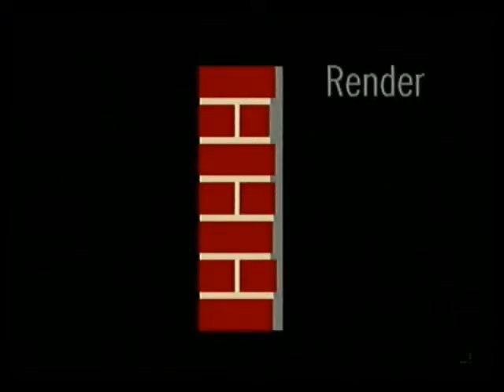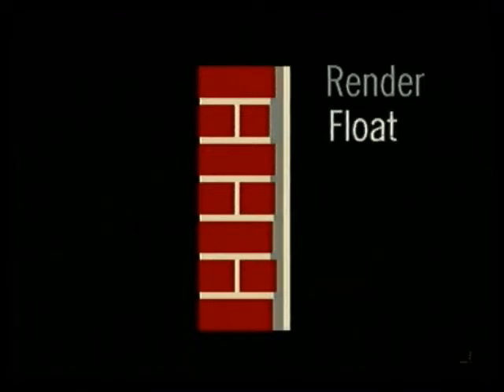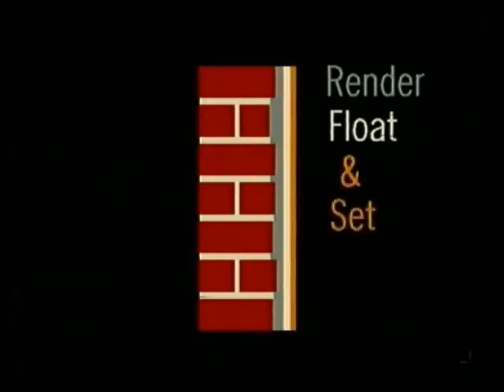Lime plaster was normally applied in three coats. The render coat leveled out the rough surface of the wall. The floating coat provided a true flat surface with uniform suction. And the setting coat gave a smooth, level surface for decoration. The thin setting coat would normally contain equal quantities of fine sand and lime. Undercoats contain coarser, cheaper aggregates, often reinforced with animal hair to help reduce shrinkage.